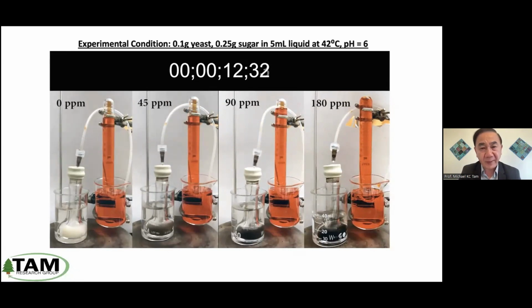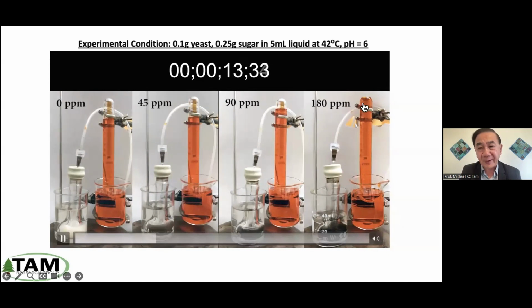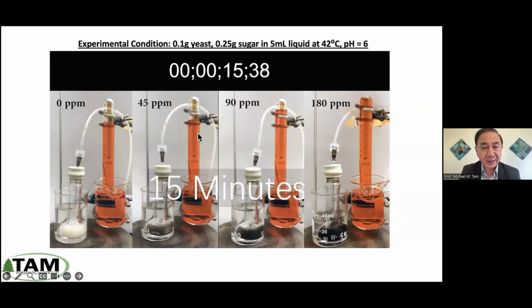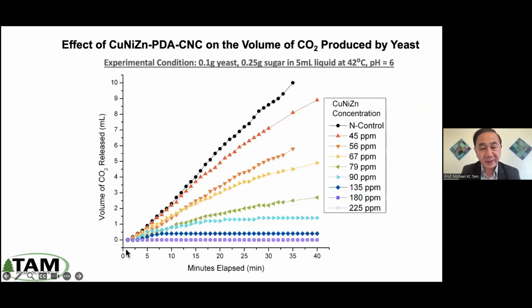As you can see, as you go from left to right, at 180 ppm, very little CO2 is being released. And from this data, we can chart this volume of CO2 release versus time. The black circle is the control without any nanoparticle. As you increase the concentration, at about 100 or so ppm, you have two results: a very large reduction in the CO2 release, and the slope is also reduced. So the rate of CO2 release and the amount of CO2 release is a function of the concentration of this nanoparticle.